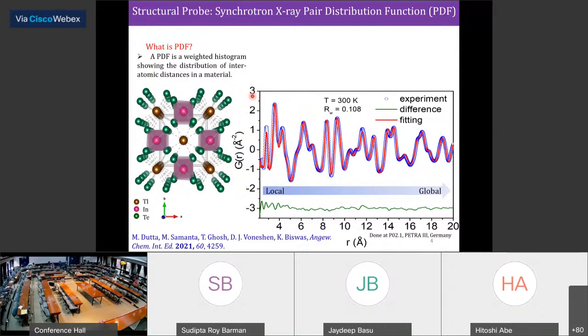When we did the PDF, we saw this kind of data, and when we tried to analyze it, we saw the first peak comes from this indium telluride bond, which is a covalent, shorter bond from this tetrahedra.